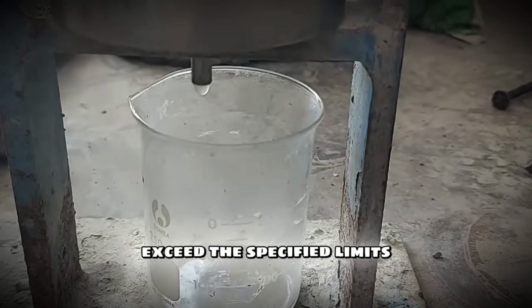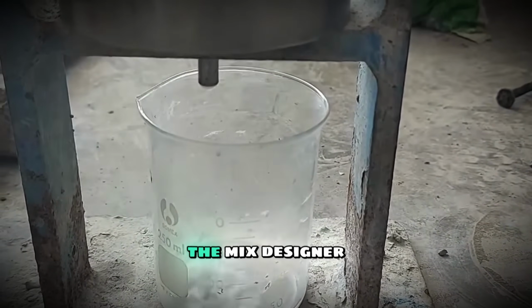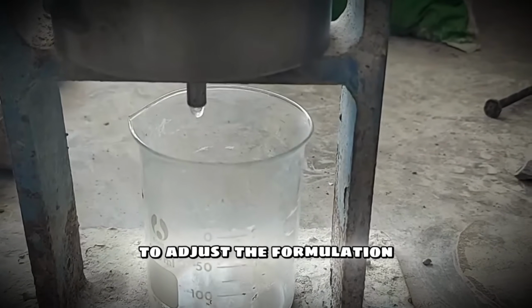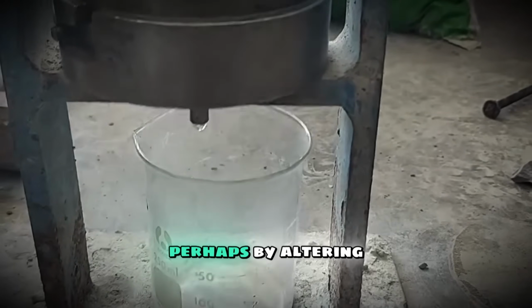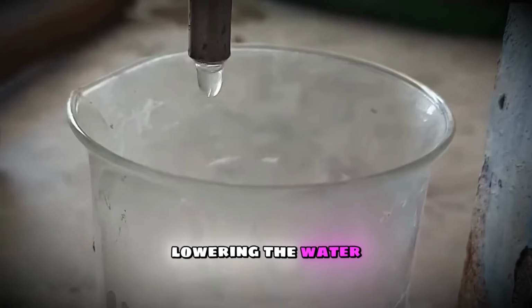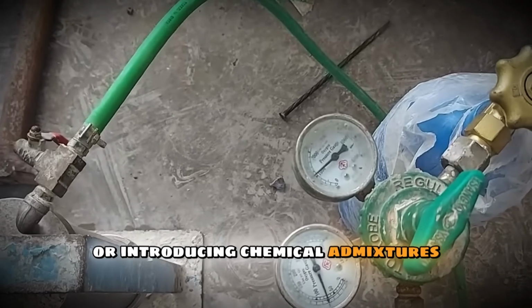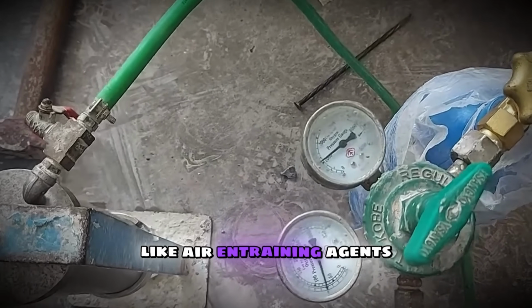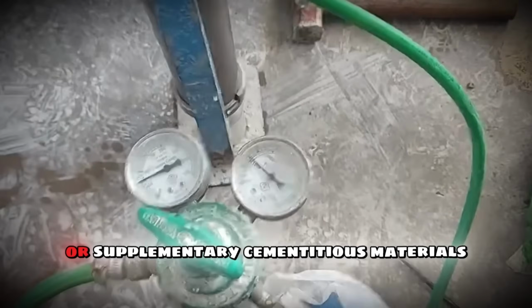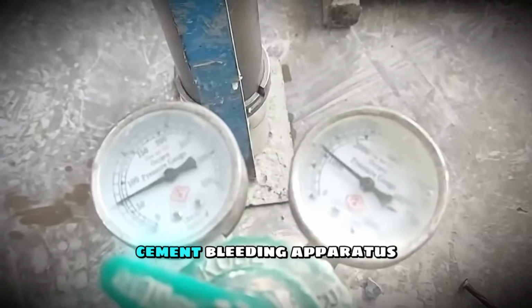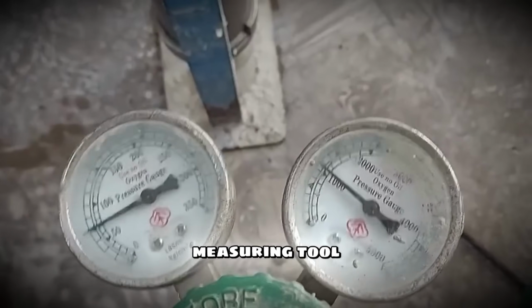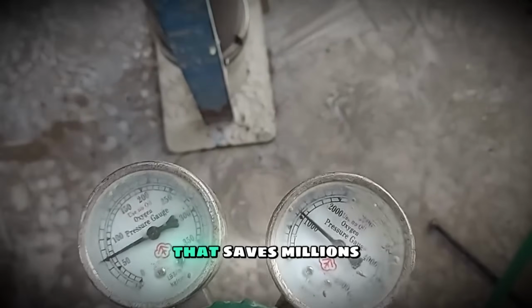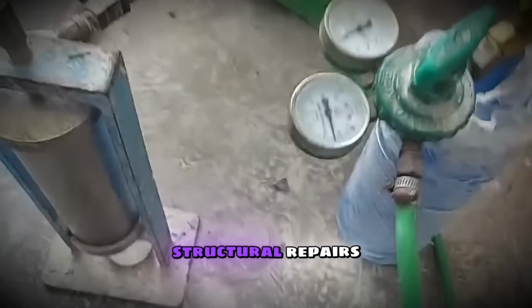If these numbers exceed the specified limits, the mix designer knows immediately that they need to adjust the formulation, perhaps by altering the aggregate gradation, lowering the water-to-cement ratio, or introducing chemical admixtures like air entraining agents or supplementary cementitious materials. The cement bleeding apparatus isn't just a measuring tool. It is a diagnostic instrument that saves millions of dollars in potential structural repairs.